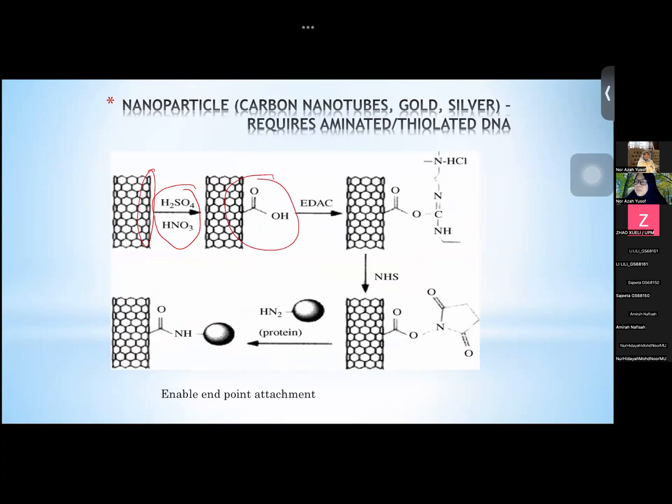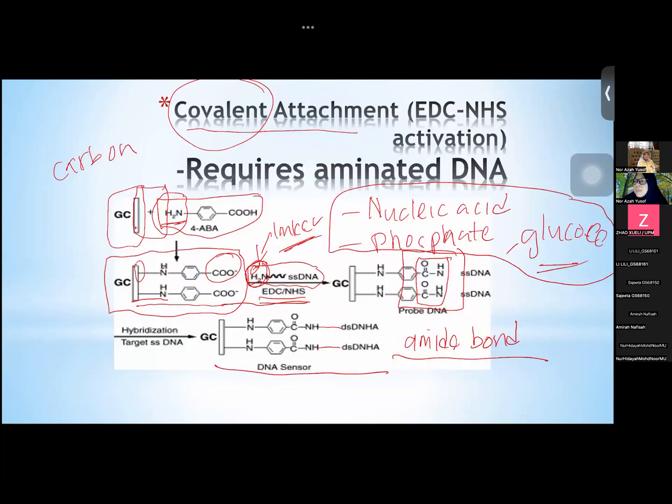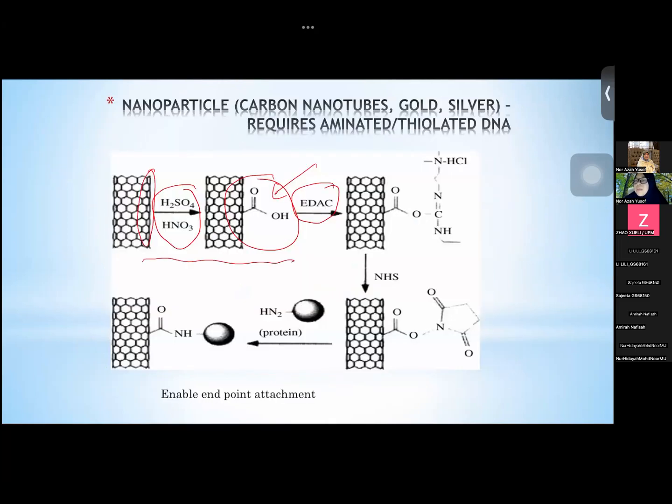You just expose, incubate the carbon inside strong acid, and then you will get this carboxyl group. Okay. So this is EDC NHS. Sometimes it is called EDAC. So you can see from here the carbon, how to attach to amine. You need to use this chemistry first.